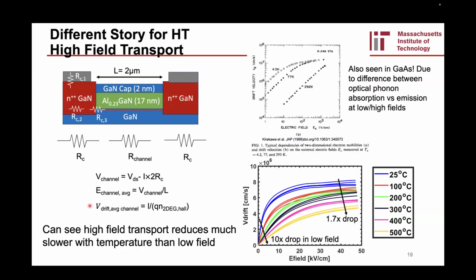All right, and surprisingly, this is actually not super new, in the sense that people see this in gallium arsenide, a little bit older semiconductor, but in the opposite direction. Gallium arsenide has a really low band gap, so you can't really use it at high temperatures, but you can measure it at very low temperatures. And so if you look at the drift velocity versus electric field, this is the log scale of it now. From 4 Kelvin to 77 Kelvin, you can see in the low field limit, the drift velocity decreases by a factor of 10. But in the high field limit, they're very close to each other. And so you see the same phenomenon occurring.